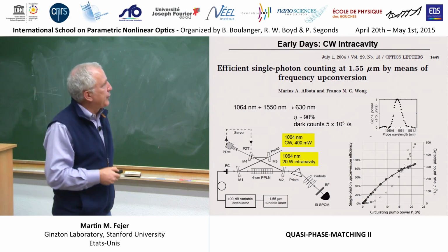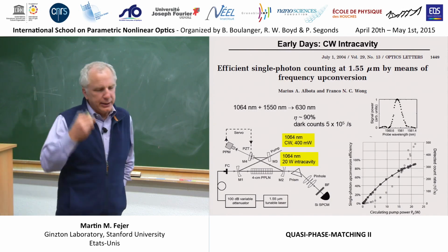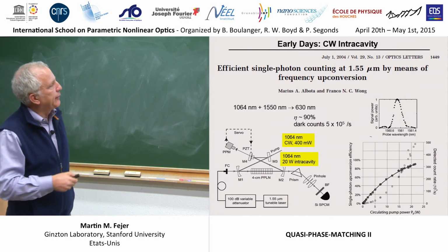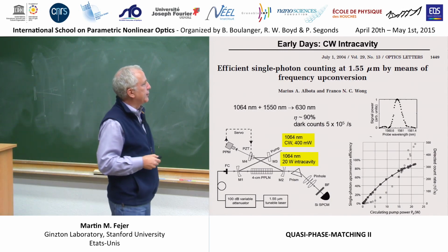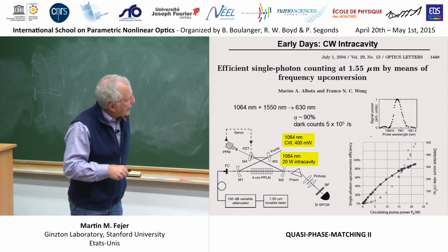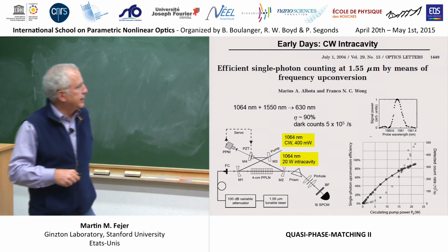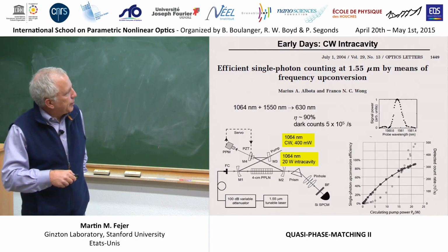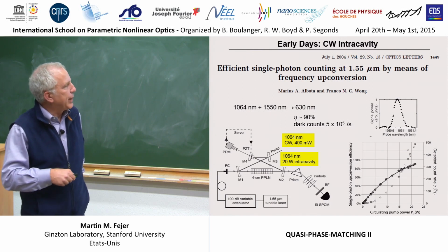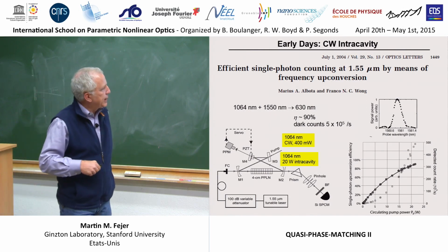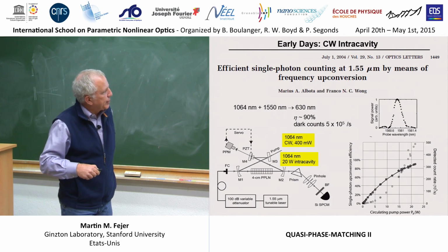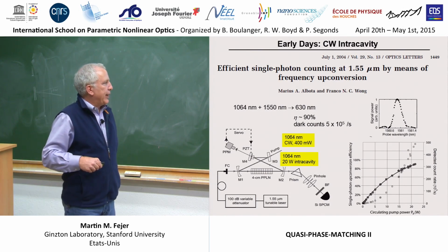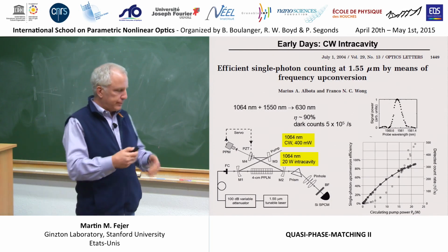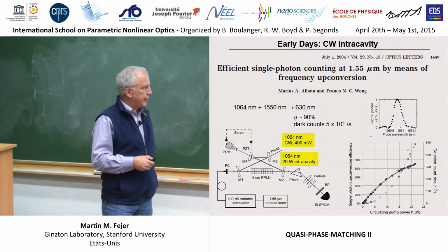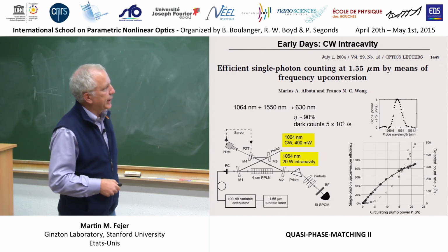So this was first tried seriously by, in a CW converter by Franco Wong's group back in 2004. He made a little ring cavity around a bulk periodically poled lithium niobate crystal and pumped it with 1064 nanometers. That resonated up the intracavity power to about 20 watts, which was what was necessary to do decently efficient mixing of a 1.55 photon and converting it up into the visible for detection with a silicon APD.